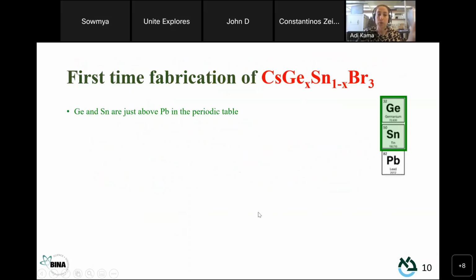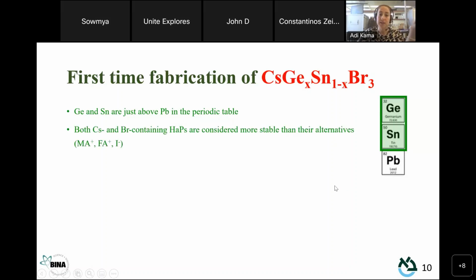So in this work, we fabricate for the first time cesium germanium tin bromide. Germanium and tin are just above lead in the periodic table and are assumed to have similar properties and high potential to replace lead. Both cesium and bromide are chosen because they are considered to be more stable than the organic molecules or iodine.